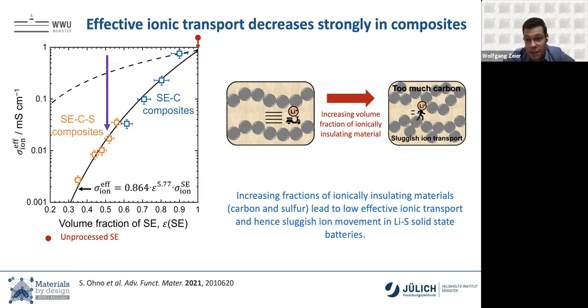That's the beauty about the sulfides. You don't have that contact resistance. They're so mechanically soft. You just squeeze them together. I didn't mention that, but this is with a chloride argyrodite. This is with a sulfide. Their bulk modulus is, I don't know, 10 gigapascal or 5 gigapascal or something like that. With just a little bit of pressure, you really compress all of the grains, and there's not a lot of grain boundary resistance in there. It's not an oxide. This is why this works.